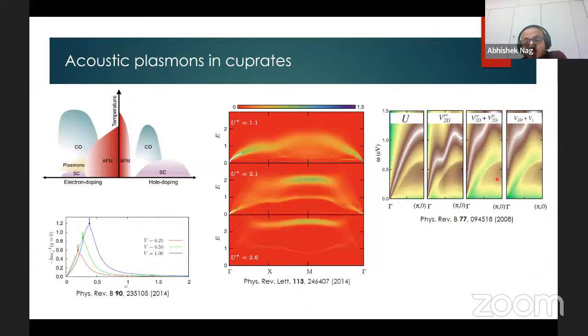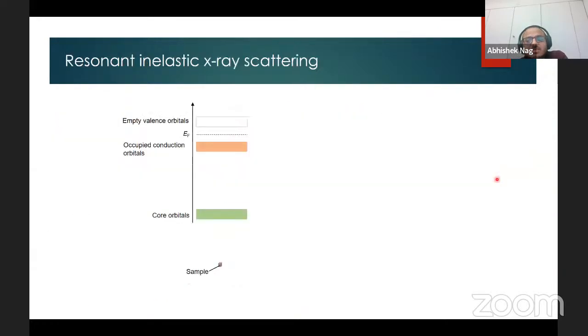So let's first take a look at the RIXS technique, which was used to observe the acoustic plasmons in the electron-doped cuprates. Here, an incident X-ray beam knocks electrons off the core orbitals of the atoms and excites them to the empty valence orbitals. Now, if one monitors the amount of X-rays absorbed in this process, one gets an X-ray absorption spectrum. Because of the hole in the core orbital, the state is extremely unstable, and therefore electrons from the occupied orbitals can fill up this hole, and this effectively creates an excitation.